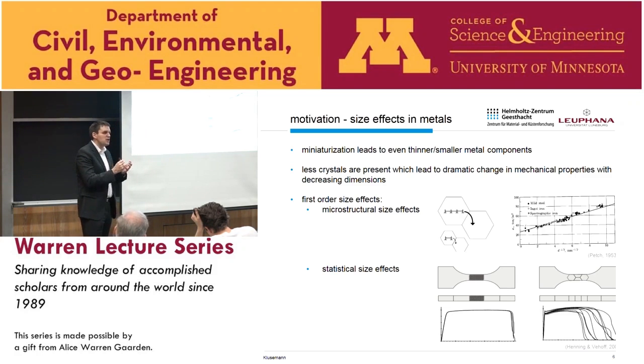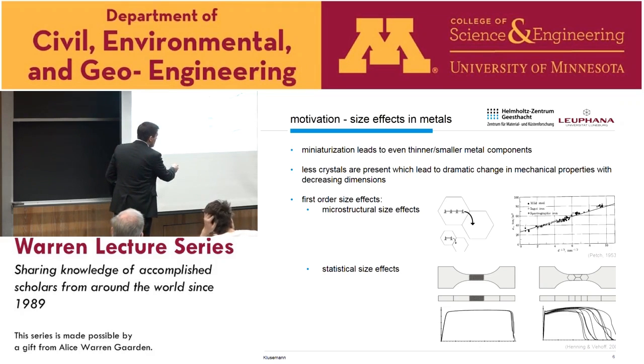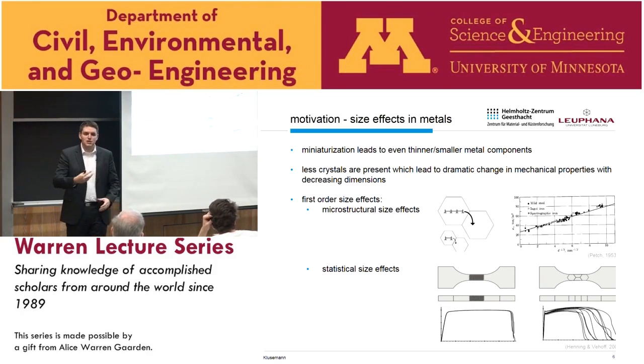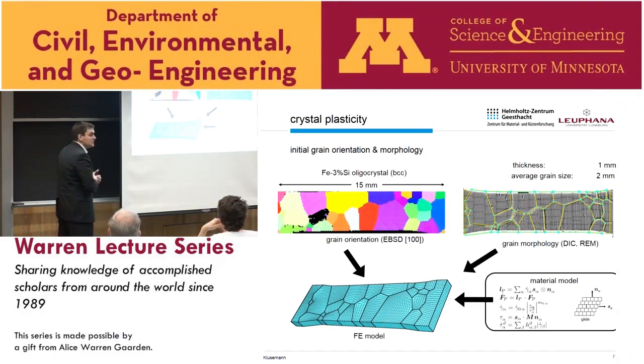However, imagine the case you have in the extreme just one grain over the width or even over the thickness. Then of course your material macroscopic response is strongly related to the orientation of each single grain. You have a very high heterogeneity of your response, even though you would say the material in general has an isotropic texture. Okay, so what we did here was an investigation of a so-called oligocrystal. Oligocrystal means a sample with very few and large grains. This was an iron-silicon oligocrystal, so it's mainly a model material, I have to say, which allows to produce